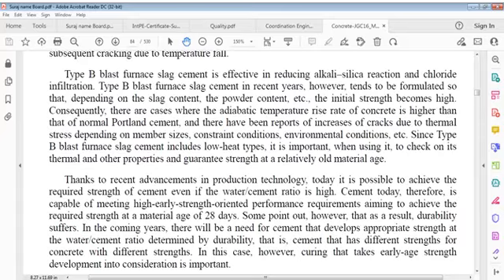Adiabatic temperature test of concrete was carried out setting placing temperature and initial curing temperature at 25 and 35. So this is adiabatic temperature test of concrete carried out at placing concrete temperature 25 degrees and initial curing temperature 35 degrees. In addition, relation between starting time of hydration heat and setting time is investigated to analyze adiabatic temperature rise equation with respect to amount of cement.